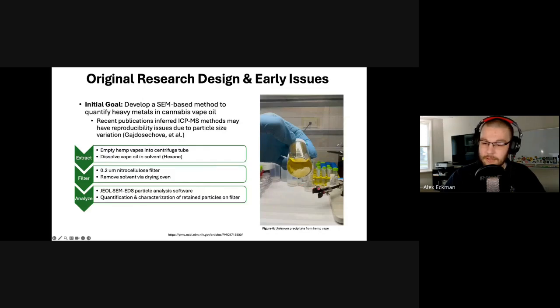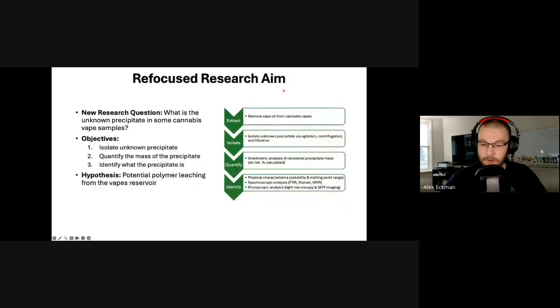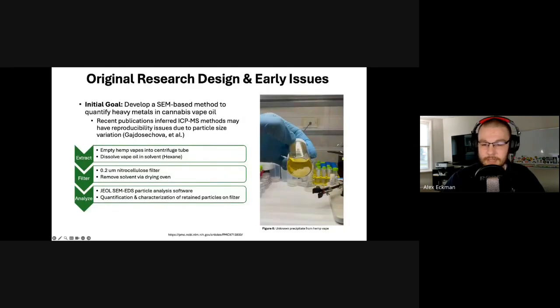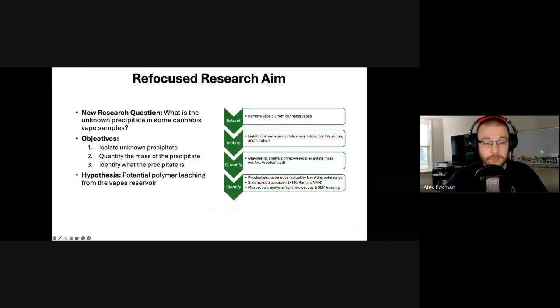But as we see here in this photo on the right, I kept getting an interesting precipitant from a handful of the vape carts. Now, being in the industry for many years, I had dissolved vape carts. I originally thought that this could be a lipid, but we were using hexane as our solvent, so that wouldn't make sense based on the solubility principles. And the big thing was this unknown precipitant was actually volatilizing under our scanning electron microscope beam. So not wanting to damage the new SEM, we figured we would take a step back and actually try to figure out what this was.